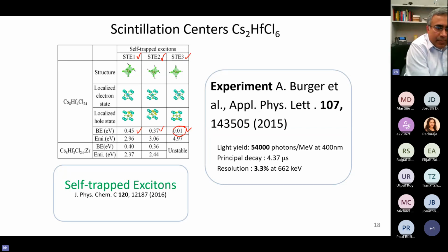And then we found their emission wavelengths, or emission energies, for STE1 and STE2 as well as STE3, although we know STE3 is not very important because it will not form under normal circumstances. I won't go into the details of their structure. The important thing is, again, we know how accurate our calculations are. So when we see numbers like 2.96 versus 3.06, we say that both self-trapped excitons have very similar, if not exactly the same, emission energy. So you won't be able to tell one from the other. They emit at the same wavelength or same energy, and they also have very similar binding energies.